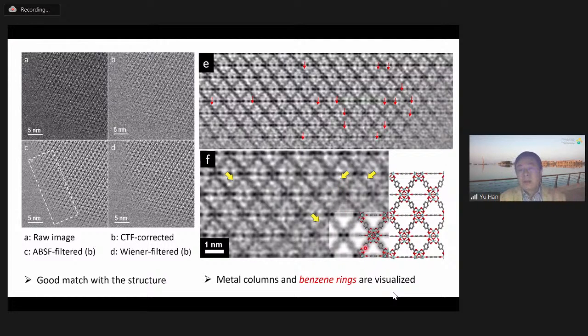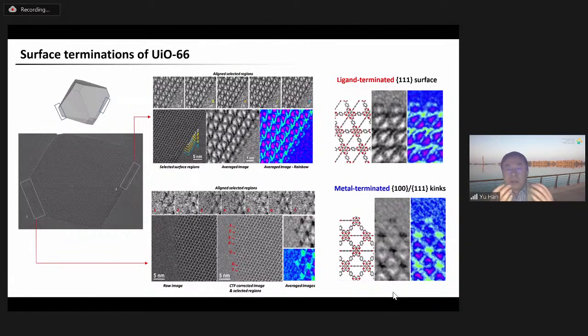Okay, so this result confirms that the crystal structure of UiO-66 is very well preserved under the ultra low dose condition we use. And after we confirm that the imaging condition is safe for the bulk structure, we move forward to look at the crystal surfaces. Interestingly, we found that the surface termination mode of UiO-66 is facet dependent.